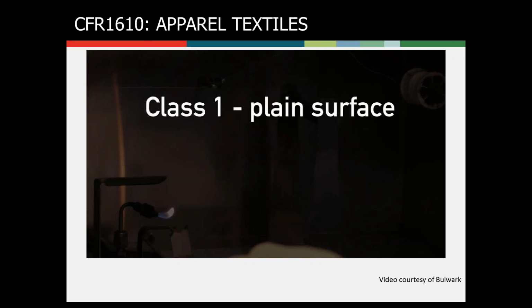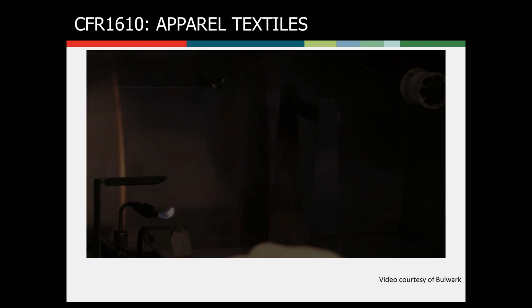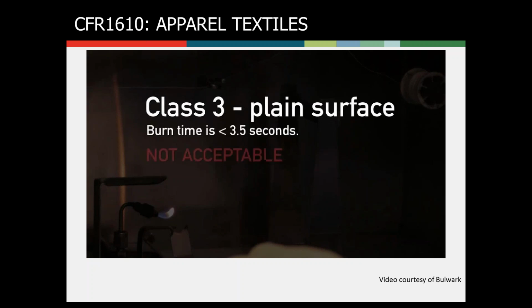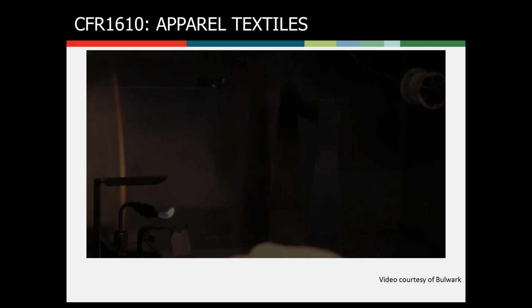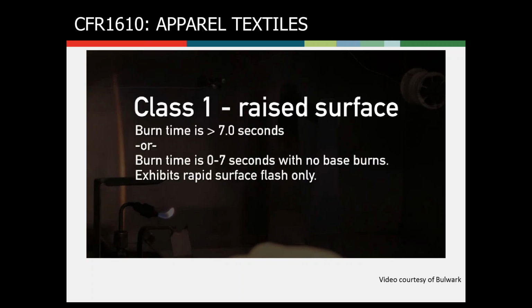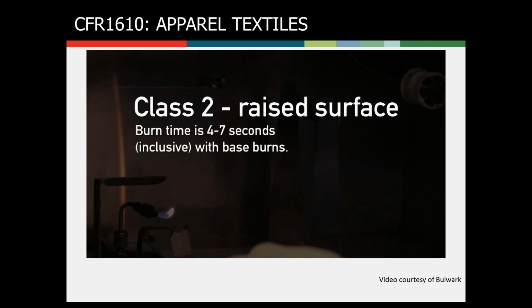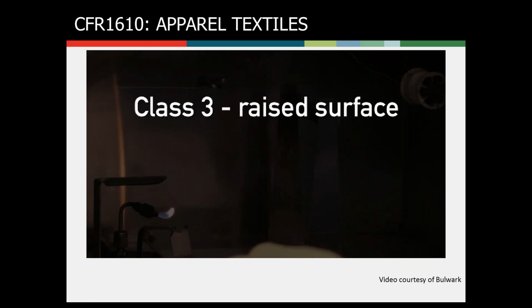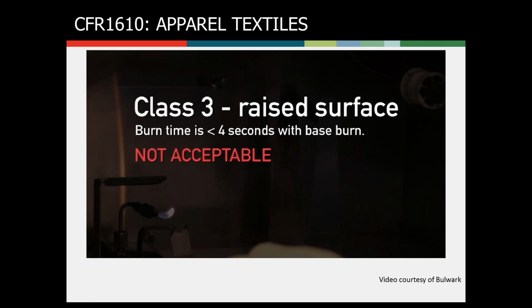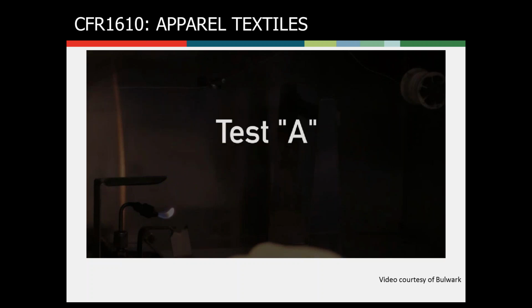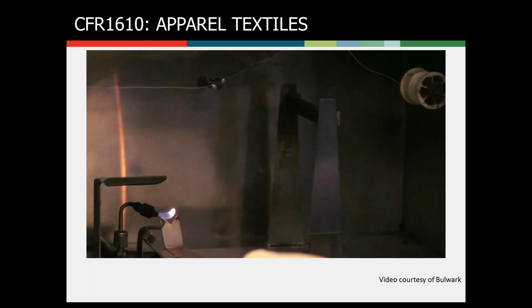So the test classifies your materials in 3 ways, class 1, 2, or 3. For a plain surface material like a t-shirt, class 1 means that your flame spread is greater than 3.5 seconds up the material. A class 3 material for a plain surface would have flame spread less than 3.5 seconds. We'll show some examples of this coming up. For raised surfaces, you get more time. Class 1 is a burn time greater than 7 seconds. A class 2 will be a burn time of 4 to 7 seconds. And a class 3, for a raised surface fabric, is anything less than 4 seconds. And so in order to pass the Flammable Fabrics Act, you've got to be a class 1 or a class 2. Anything that's a class 3 is not acceptable in the standard.